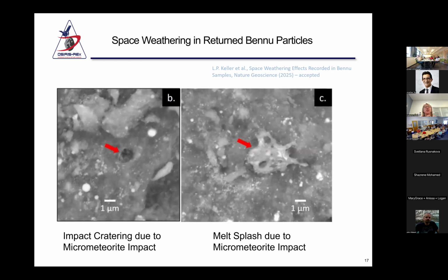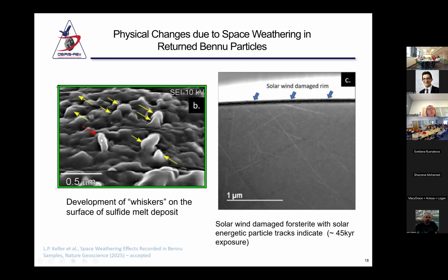So we just finished analyzing the surface. Some of these are TAGSAM head particles, and some of these are contact pad particles. Here we are looking at space weathering effects, and what we're finding is that there has, in fact, been space weathering on the surface of Bennu. What we see here are impact craters created by small micrometeorites. We see splashes where the micrometeorites impact the surface and then heat up and melt, creating these little splashes. We see all kinds of interesting features, including the formation of these little whiskers, sulfide melts on the surface where you have an impact, and the fingers also have a different composition than the host material.